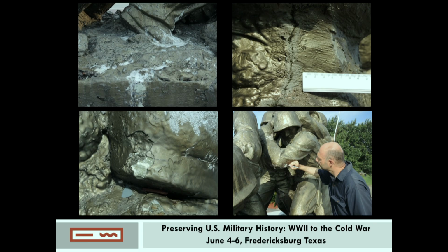The surface was coated with thicker and more impermeable coatings in an attempt to fill the cracks and stop the deterioration, which was constant. The cracks were filled with various patching materials, including polyurethane foam, polyester resin, different kinds of cement, wood, and cork. We found all these materials during the restoration. Unfortunately, it didn't work.